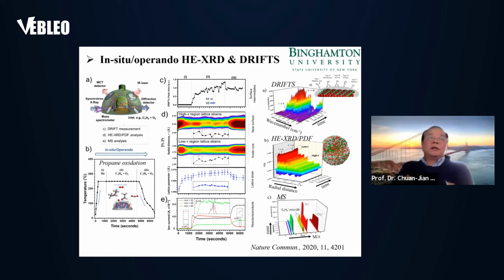And more importantly, those species demonstrate a type of regular or irregular, a mixed oscillation, okay? And then if you look at the crystal structure in the middle, in the D, you can see they also display a certain degree of oscillation. The red color is strongest intensity, the yellow weak, the blue is the weakest one. You can see it also oscillates, the metal bond distance.